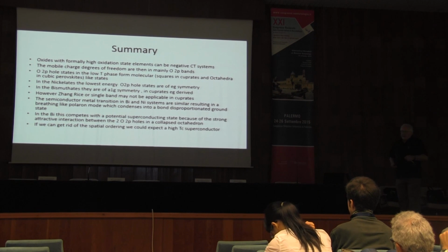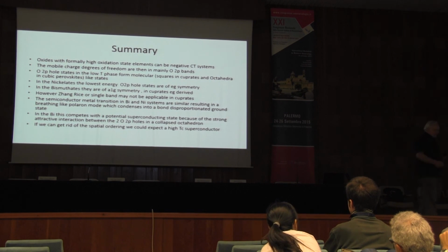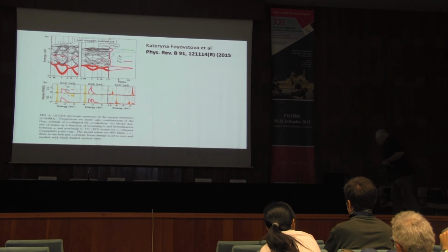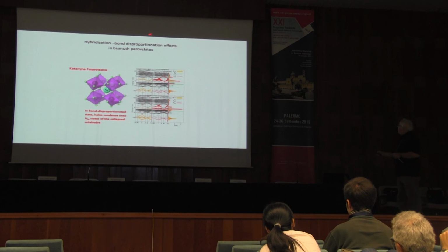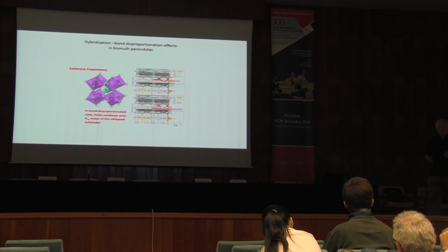Okay, so there is a link between all of these materials. I should have said that there are exactly 2 holes per oxygen octahedron in that empty state. That's why you have a gap. These are bipolarons. These are 2 holes in an oxygen octahedron, but these are bipolarons which have crystallized out in a charge density wave, or whatever you want to call it. It becomes a molecular density wave, actually, in this crystal.